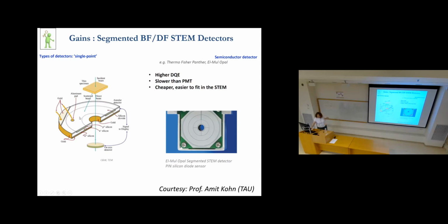So when we scan the sample with a beam, we may acquire a series of images from the electrons scattered by this angle range, and by this angle range. And in addition, with the bright field detector on axis, we can acquire the electrons scattered along the optical axis. So when this beam scans the material, the electrons are scattered due to numerous interactions happening in the material. And with our previous configuration, we always acquired only those electrons which were scattered by high angles, because the detector is a big hole here and only one angle range outside.